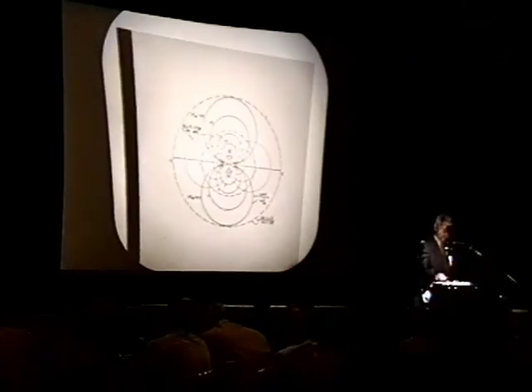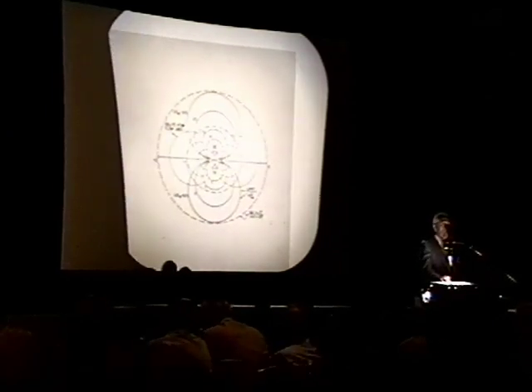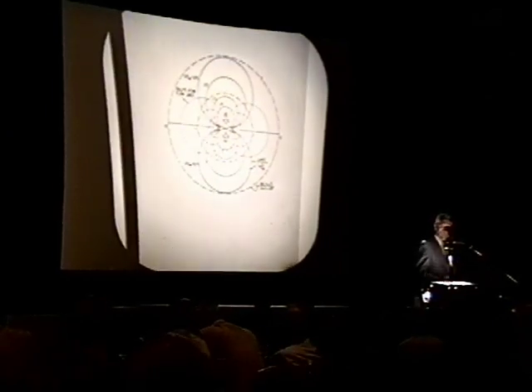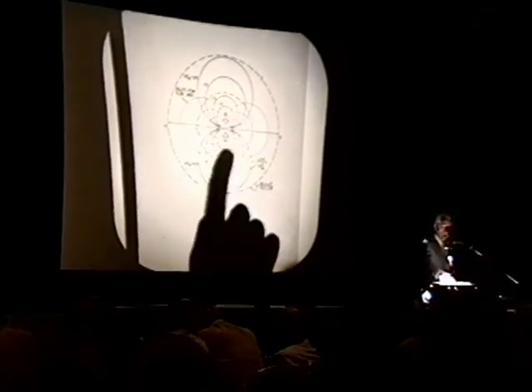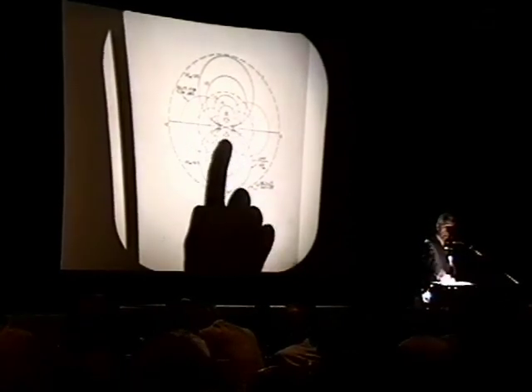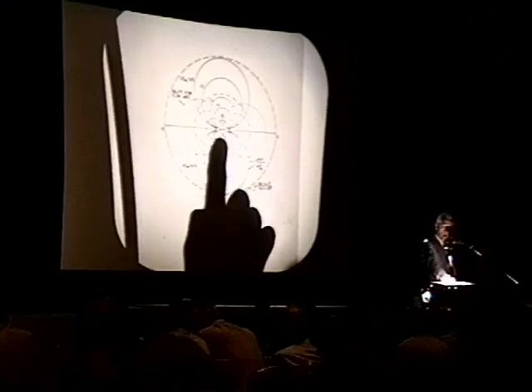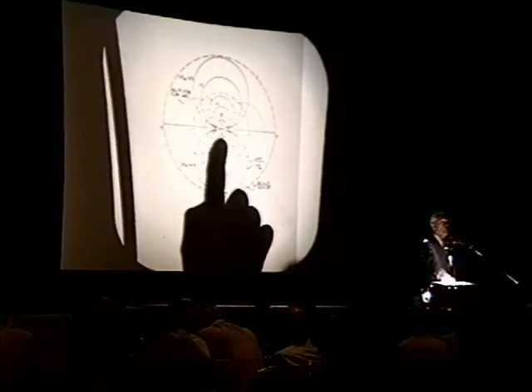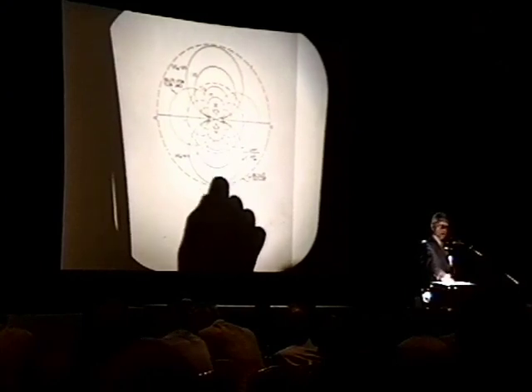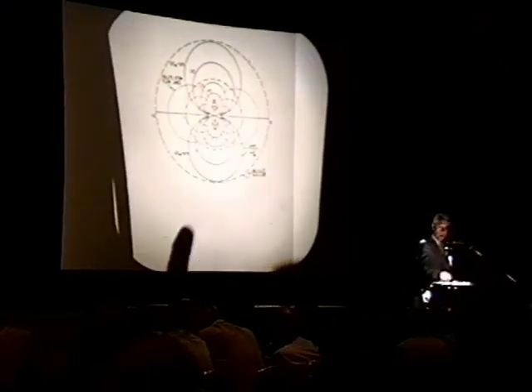Because of the interest shown yesterday, I put in a slide about what happens around a dislocation. One can calculate the stress distribution about a dislocation, therefore the chemical potential, and the concentration of hydrogen at a constant chemical potential everywhere around this dislocation. It's an edge dislocation. We have a dilating field on the lower side. The missing line of atoms is on this side. Here we have a compressive field.